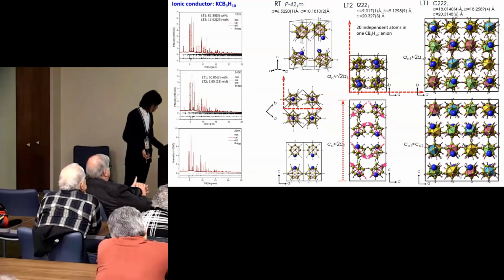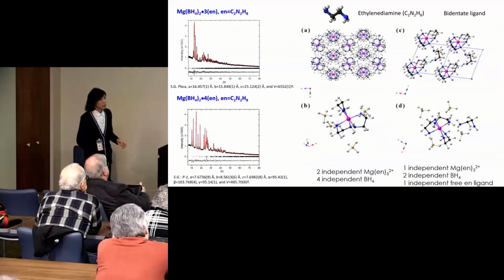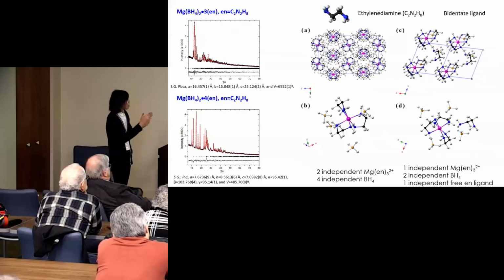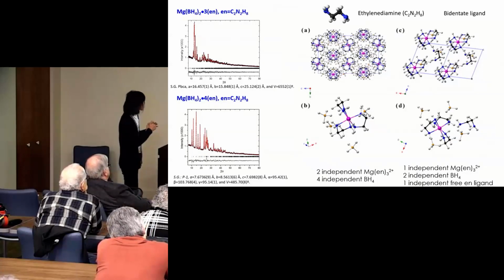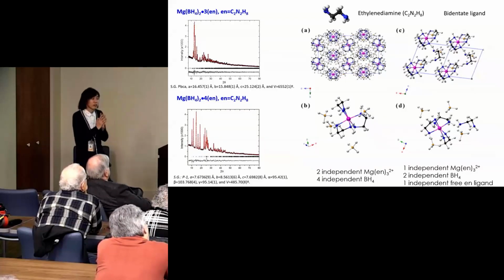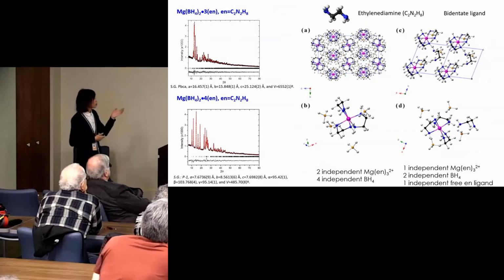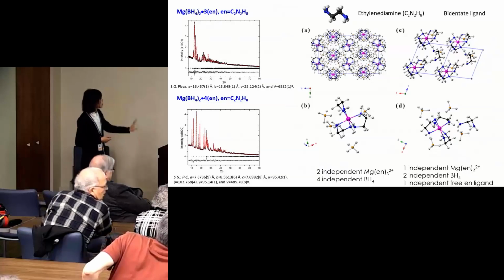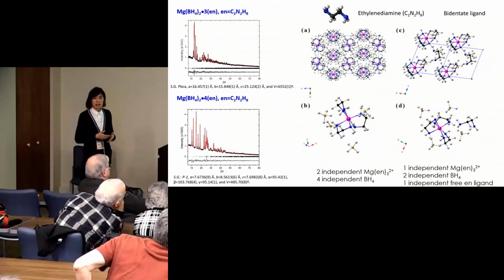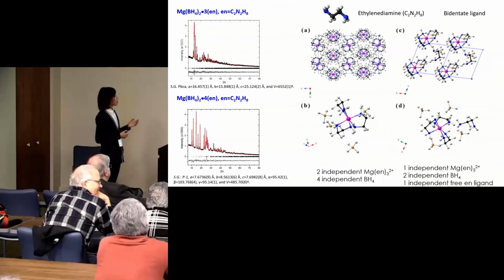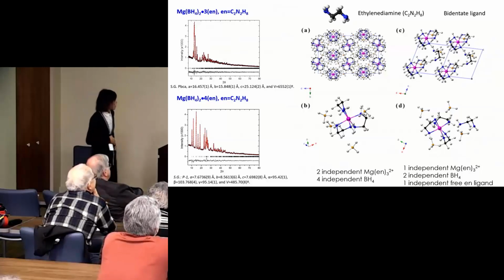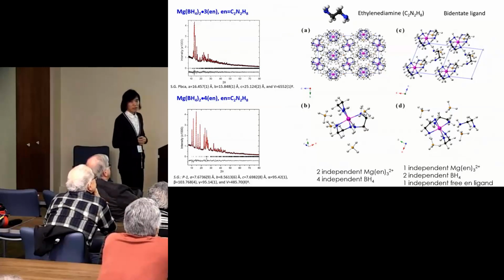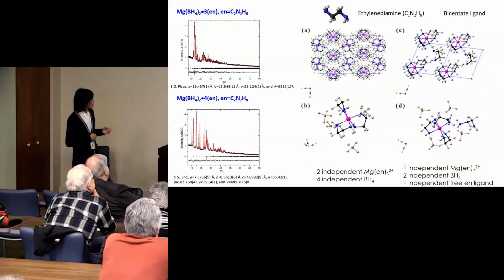on X-ray diffraction data. Another example is magnesium borohydride adduct with ethylenediamine. This compound contains a lot of hydrogen, so it can be used for hydrogen storage. And also, more recently, other researchers found that this compound can also exhibit conductivity at high temperature. So again, we only have lab X-ray powder diffraction data, and